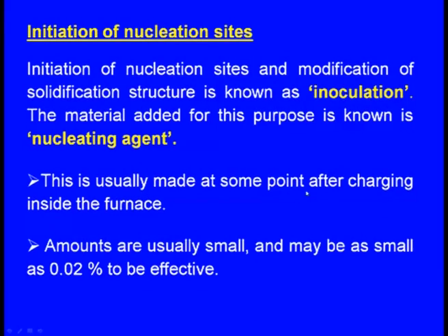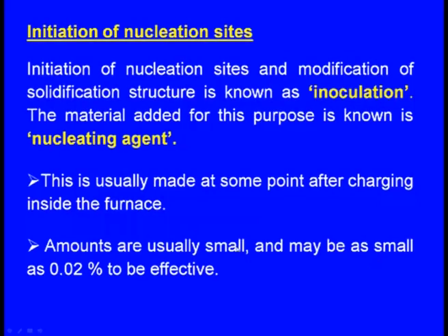In the first case, we have seen the alloying elements we were adding. Here, we will be adding nucleating agent so that the solidification structure will be changing, so that the solidification structure will have better properties. This is usually made at some point after charging inside the furnace. Now, amounts are usually small and may be as small as 0.02% to be effective.